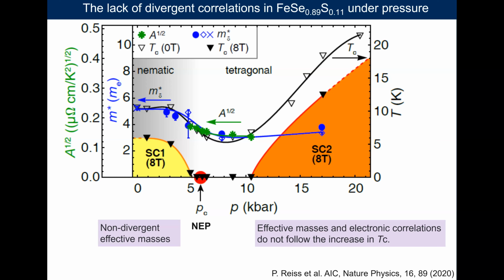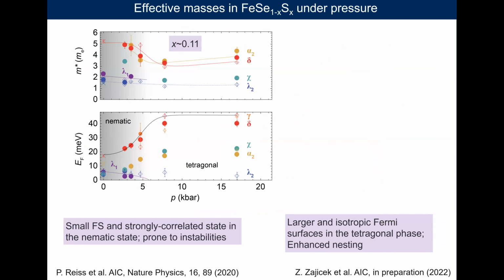Unusually, what happens to the effective masses correlates very well with Tc in this regime. Whereas as we go to higher pressure with higher Tc, the effective masses are actually not growing that much anymore. It seems to be a surprisingly low effective mass at high pressure, when Tc increases by a factor of 3. So this is something we are trying to work out, why this is the case.